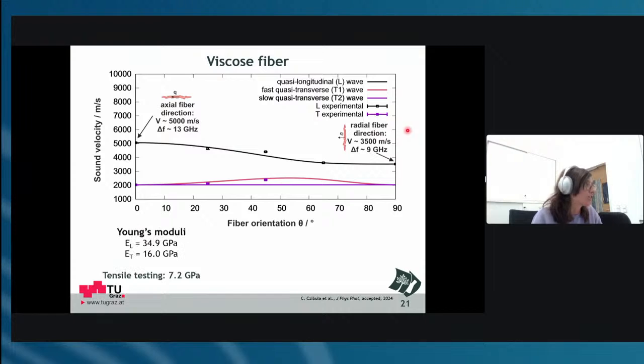Now we can apply these formulas from before and get the Young's moduli in the axial and the radial direction, the shear modulus, because here, as I mentioned, we have only one transverse peak, so C44 is assumed to be C66, that the two of them are equal, and then the Poisson's ratio. You see the big deviation is in the Young's moduli actually. They are much higher in the Brillouin measurements for the longitudinal direction.